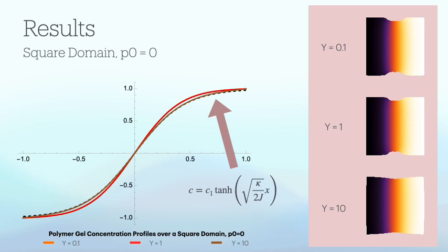On the left is a plot displaying the concentration profiles of these conditions, with the black dotted line being the expected curve for a concentration profile without swelling pressure. This concentration curve is the tanh profile expected for an infinitely wide, completely rigid material. All of these curves are symmetric, which makes sense based on the energetic costs of the negative C1 and C1 energy basins, as noted previously, and as shown in the images to the right. So our model appears to be reliable.